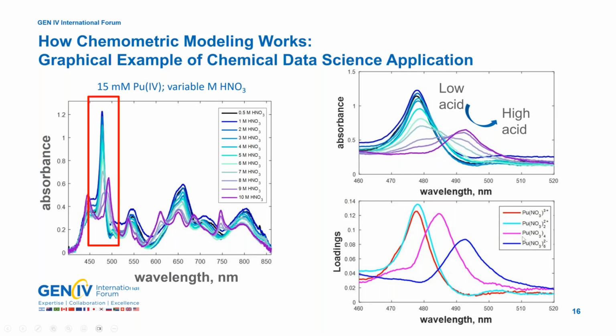Now, what's even more fun from a chemist perspective, in terms of the type of information we can pull out, is this little shoulder right here on this red band for the mononitrado species, right at about 470 nanometers. That shoulder actually overlays very nicely with where you'd expect the fully aquated species of plutonium-4 to be, so right before that mononitrado species comes in.